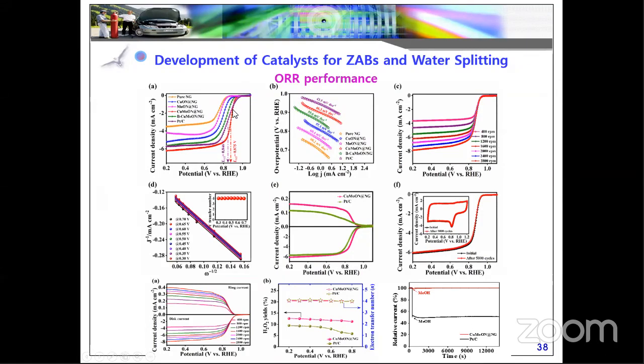So the catalyst is first confirmed by ORR performance, because ORR is one of the kinetic issues, and this ORR performance involves sluggish kinetics reactions. So we want to compare the ORR performances with the commercial catalyst, platinum carbon. Our materials have a half-wave potential, E1/2, which is a very important value, and the E1/2 value compared to the platinum carbon based materials is lower. And the onset potential is also lower than the platinum carbon.